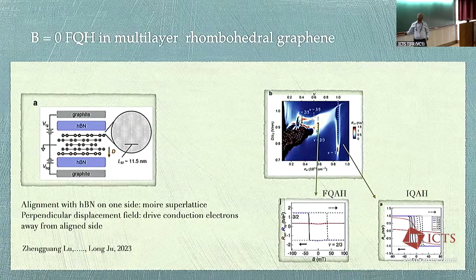So here, say in this picture, there are 5 layers of graphene sheets stacked in a particular way, and the experimentalist can apply an electric field perpendicular to the stack, so as to drive the conduction electrons far away from an hBN layer that's nearly aligned with the topmost graphene layer. So there's a Moiré potential that's sitting here primarily, and the electrons are primarily sitting here at these displacement fields. And then you see pictures like this.